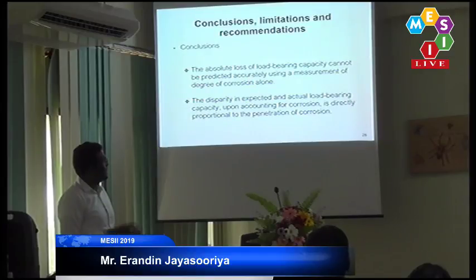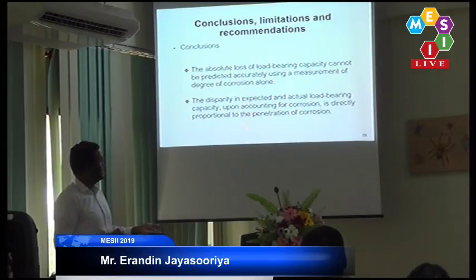Obviously, the expected versus actual loads are different. That was a real eye-opener. But more importantly, we could successfully prove our hypothesis that this disparity in the two loads was relevant to the penetration of corrosion. There might be other factors as well, but we started out with this factor and it showed quite a nice proportionality.